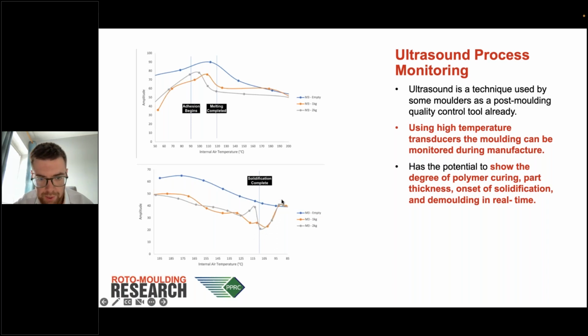And interestingly, that then shows the shrinkage, and this point shows the warpage and how the molding is changing. So it started to release, and then a different area of the molding then changed shape, and it then made contact with the mold again to dampen the sound signal.